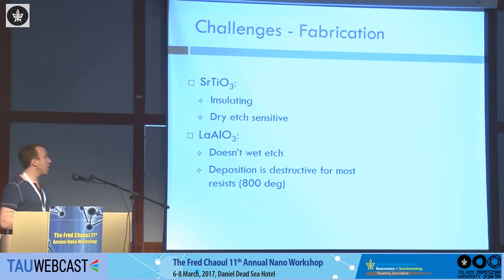The challenges, on the other hand, are really big. First of all, STO itself is insulating, so it's really hard to write on it with the E-beam. Second of all, it's dry etch sensitive, so if you ion mill it, it will become conducting. Third, LAO doesn't wet etch at all, so it's really hard to work with. And the deposition of LAO at 800 degrees is destructive for most resists. So it's really hard to work with these materials.